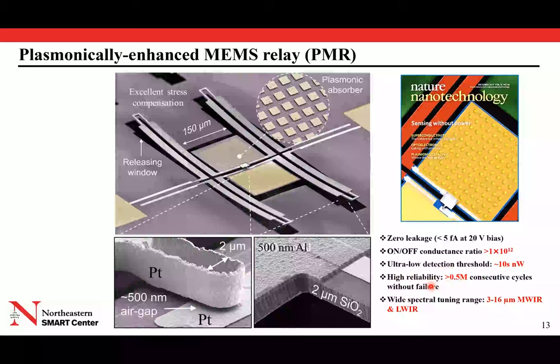We tested the reliability of these switches. We measured over 500,000 consecutive cycles without failure. So we don't know what the failure mechanism is and how many cycles they can survive. While we developed that project under the DARPA program, we stopped at that point because that was already sufficient for the applications that we have in mind. Remember, these are switches that are not meant to switch all the time, right? They are supposed to detect events that are time critical, but relatively rare, right? So 500,000 cycles, if you do all the calculation, would already be longer than the self-discharge of the battery that you're using there, right? But certainly from a more fundamental standpoint, we would be interested in learning more about failure mechanisms, et cetera, of this structure.